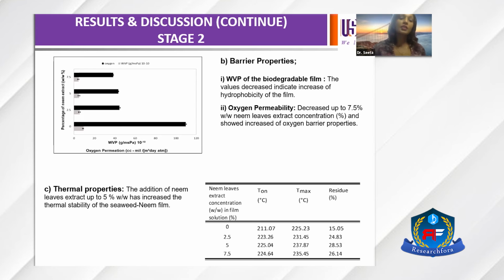Then the next one is the thermal properties. I used TGA, thermogravimetric analysis, to analyze the decomposition and thermal stability of the film. Up to 5%, there is an increase in thermal stability. You can see the T onset and T maximum increased at a higher neem leaves concentration. This is because the addition can cause hydrogen bonding, and the thermal stability also increases.